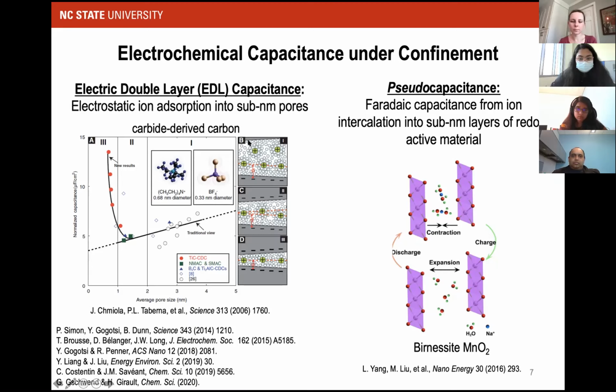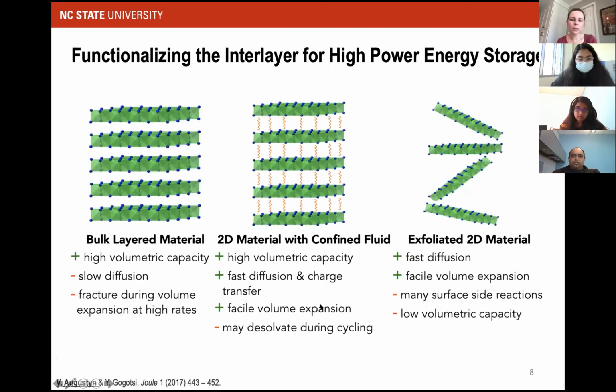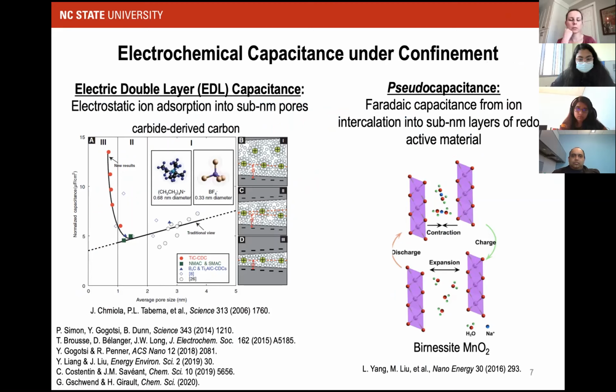How would you distinguish between a contribution from double layer capacitance and a contribution from pseudocapacitance at various potentials? In some cases, it's very easy, if the pseudocapacitive process is purely like a hydrogen adsorption event or something that's very clearly distinguishable from the cyclic voltammetry signature. In other cases, you don't really have an easy way of distinguishing them. And one of the points of this presentation is that maybe you don't need to distinguish between them because they contain features of both. That's kind of the story of birnessite.